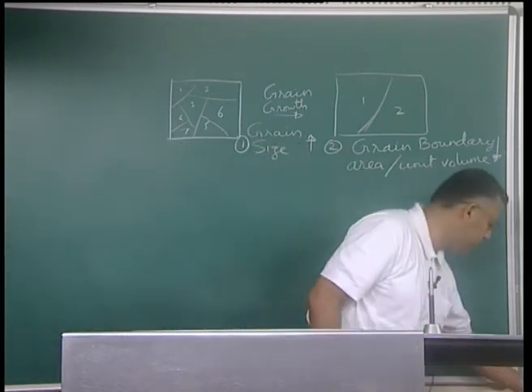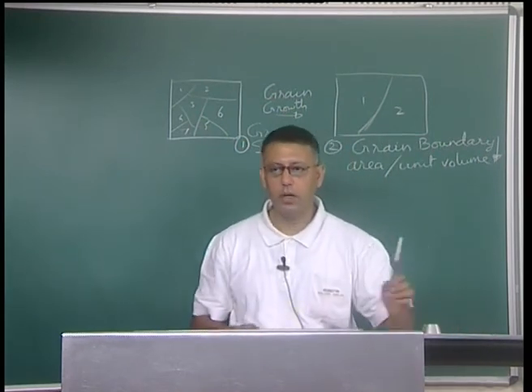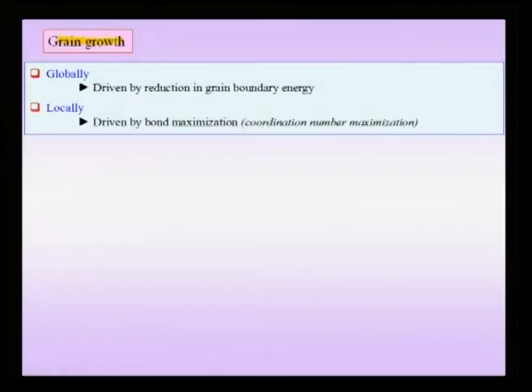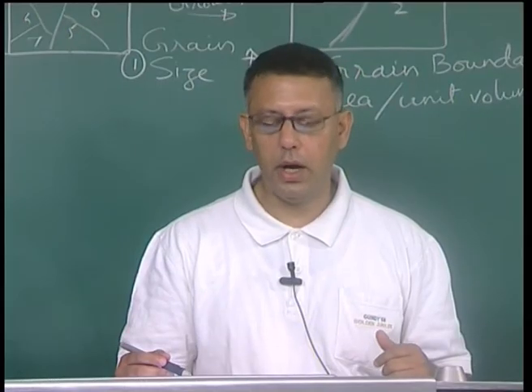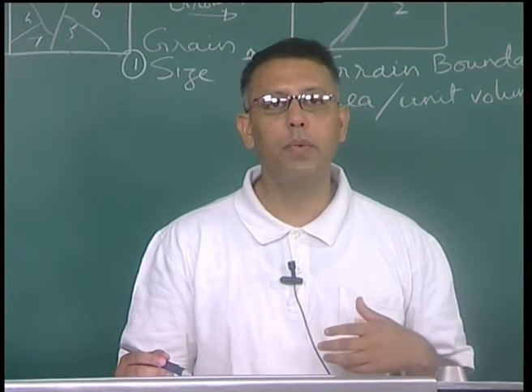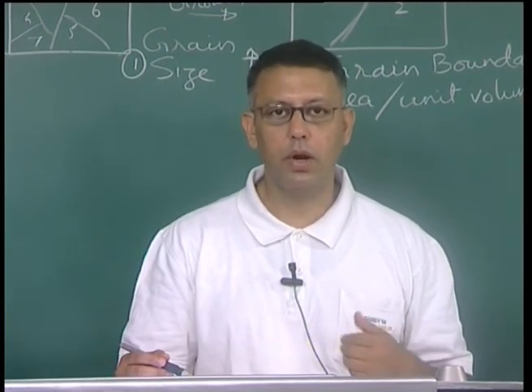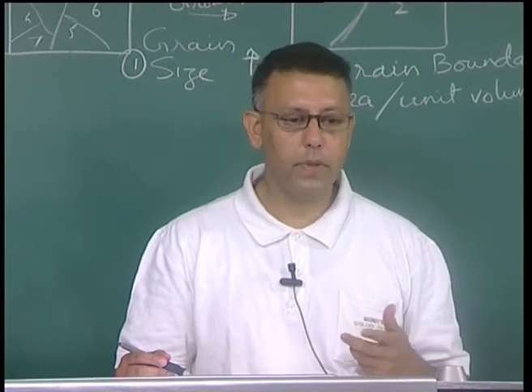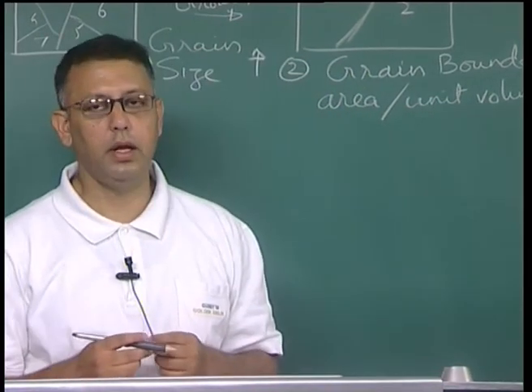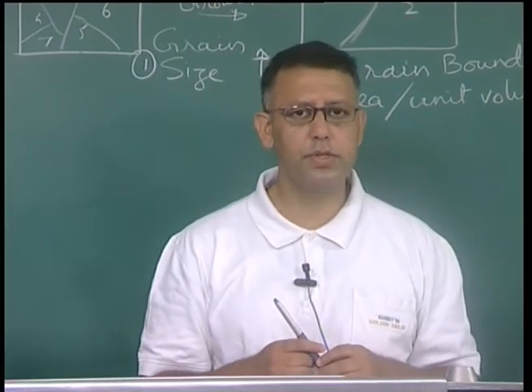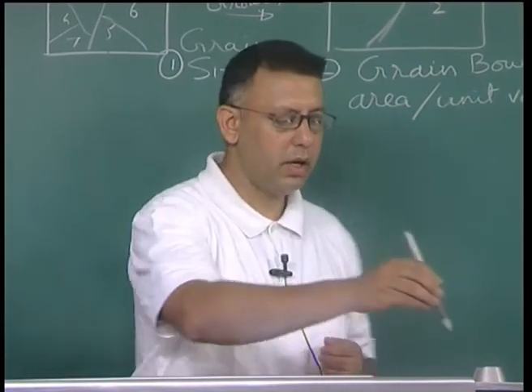Now, what drives this process globally is very clear. It is a reduction in the grain boundary energy. So, globally it is a reduction in grain boundary energy which drives this process. But for every process to take place, we have to worry about two criteria. One is known as the global criteria, which is typically a thermodynamic criteria, but additionally we also have to worry about a local criteria, which sometimes may behave like a stress or a stress intensity, or even like a local energy density criteria.